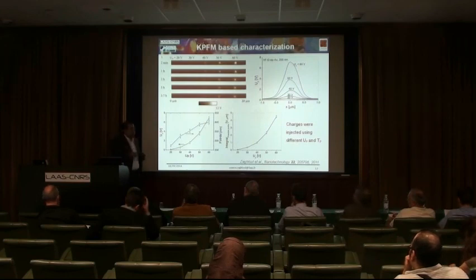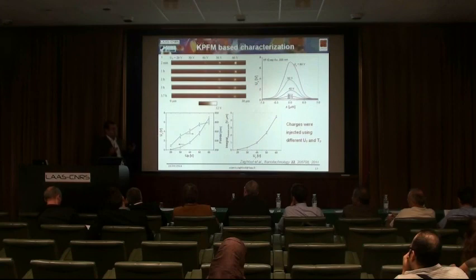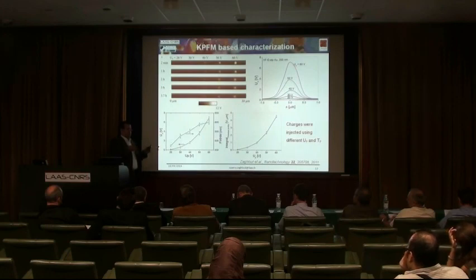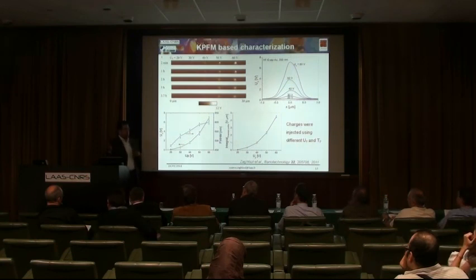This scale of 1 nanometer and 2 nanometer we still could do easily using very fine tip. Is there something like that? Yes, of course. There's many tips right now which is based on carbon nanotubes, where you can use it and then you inject a charge with it. And in this case, I expect, based on a discussion with a colleague from a company developing these tips, we could have around 10 nanometers, might be like 50 nanometer or so. So the message here is, yes, this is not really a nanoscale, but this could be done using other tips.